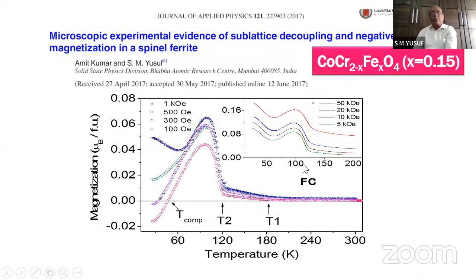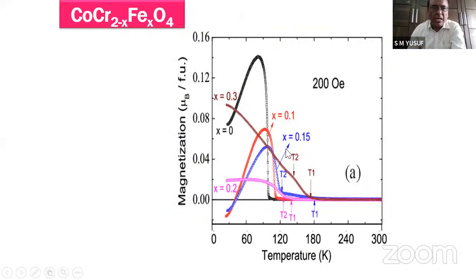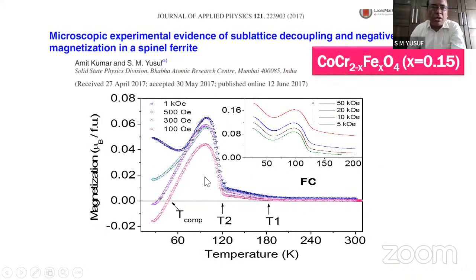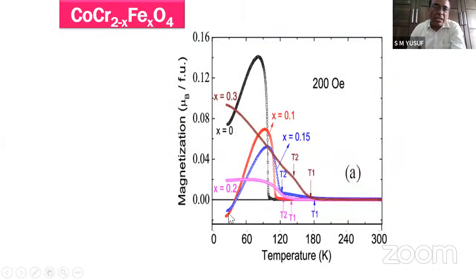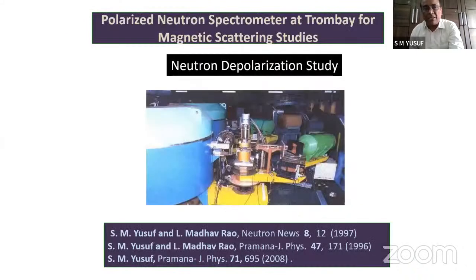Now I show another example, a ferrite system based on cobalt, chromium and iron. Here again you see the similar observation of magnetization reversal very clearly, and field dependence is also seen. This is for one of the compositions, particularly 0.15 in this series, but you see the full series data. Only for particular compositions, that is 0.1 and the blue one, 0.15, you see reversal, but not for other compositions. Basically, you need to have the balance between different magnetic sublattices. That means you need the right kind of composition balancing, and only then will you see this behavior of magnetization reversal.